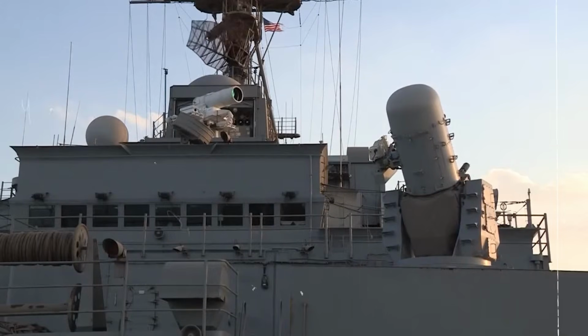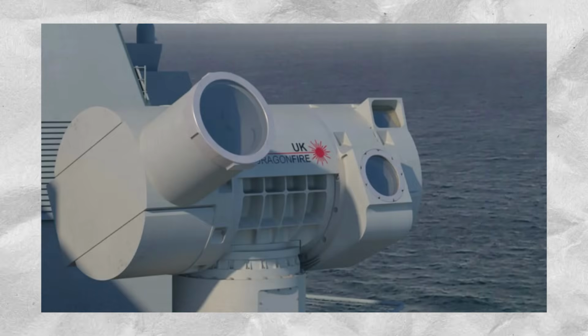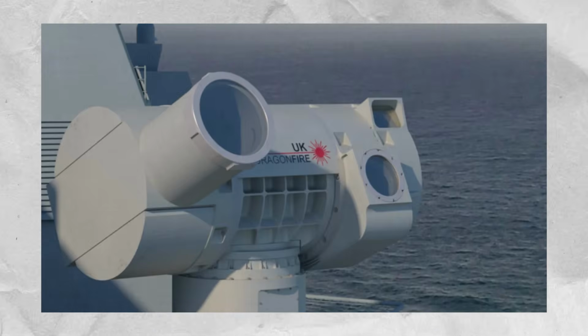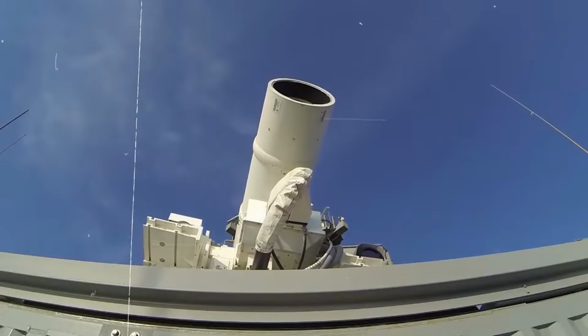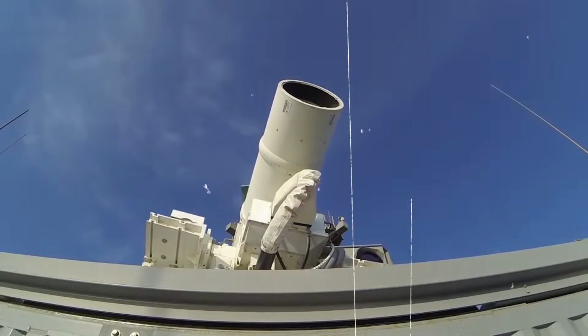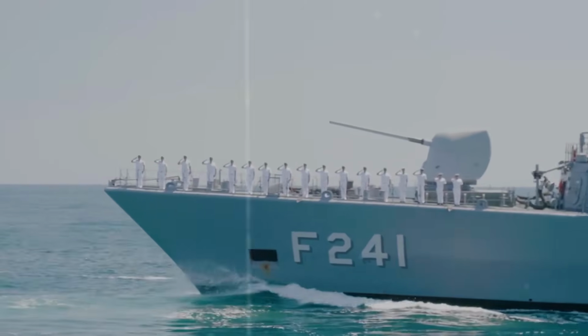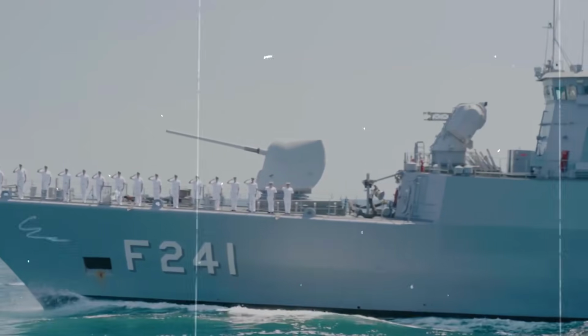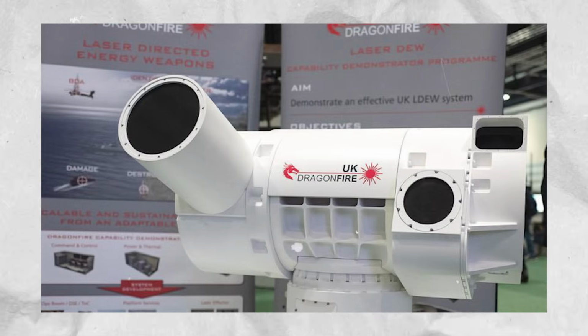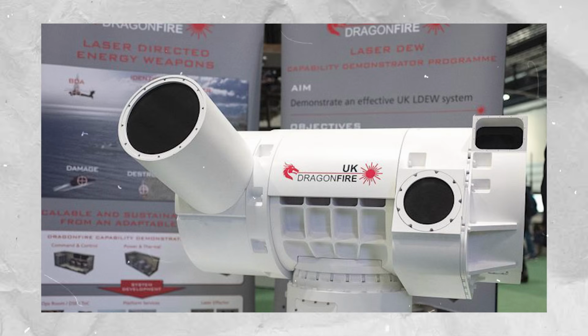At that temperature, an exothermic decomposition reaction begins within the cell chemistry that generates more heat than the laser is delivering. The runaway propagates through the battery pack autonomously. The laser does not need to maintain dwell after runaway initiates. The kill is self-sustaining. The flight controller loses power as cell voltage collapses. The motors lose their control signals. The drone departs controlled flight.